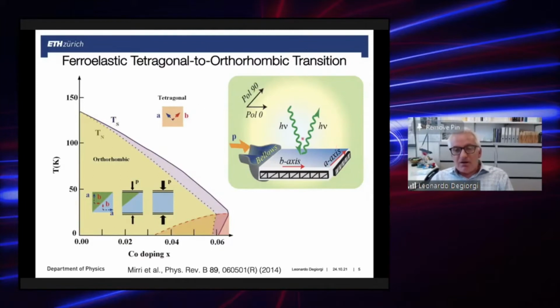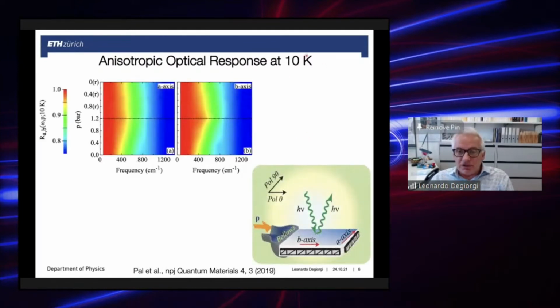Now, let me show you, first of all, the data which were collected for this optimally doped compound at 10 Kelvin, so deep into the superconducting state. Tc here is 38, as I said before. What I'm showing you here with this color map is the measured reflectivity for both crystallographic axes. So with light polarized along the elongated orthorhombic axis or the shorter orthorhombic axis, which may be stress-induced, as I said, and as a function of the applied stress, which can be tuned in a controlled way, as I said before, in situ.